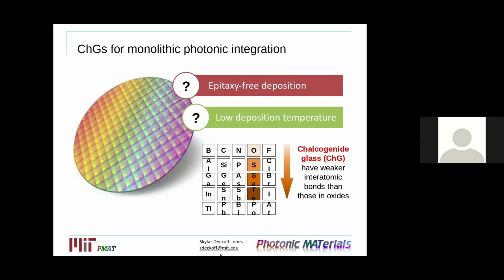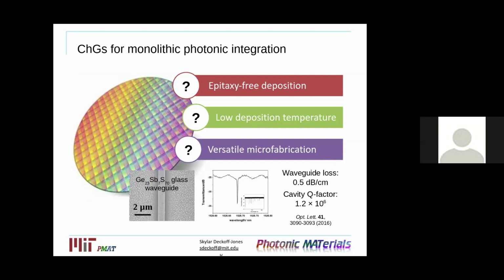However, another key advantage of the chalcogenide glasses is their epitaxy-free and low temperature deposition. So this is really what enables us to create waveguides on top of the 2D materials. They can be deposited on substrates at room temperature without actually heating the sample. So you don't need to worry about damaging the oftentimes fragile or reactive 2D material beneath. Additionally, our group in the past has demonstrated very high quality waveguides with very large quality factors. So you won't be sacrificing the quality of your waveguide as well.